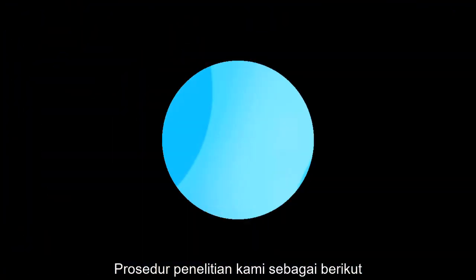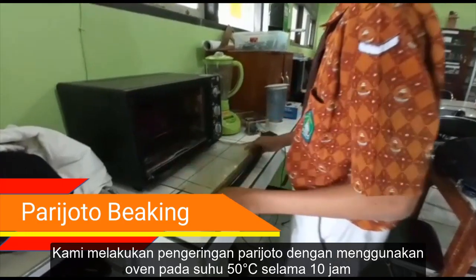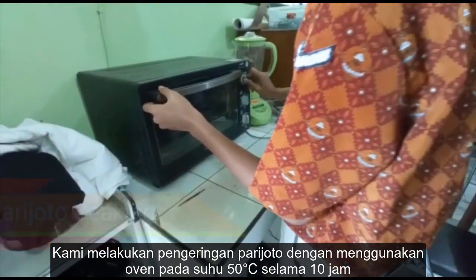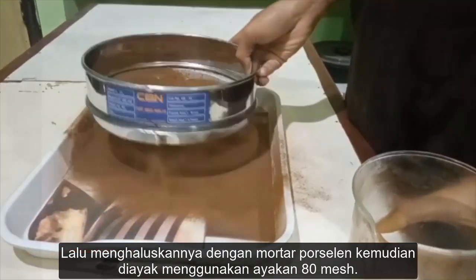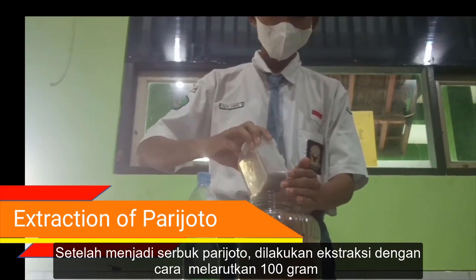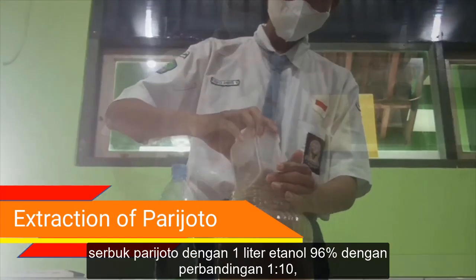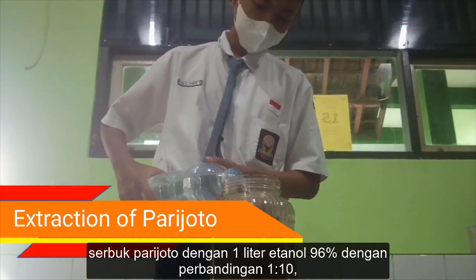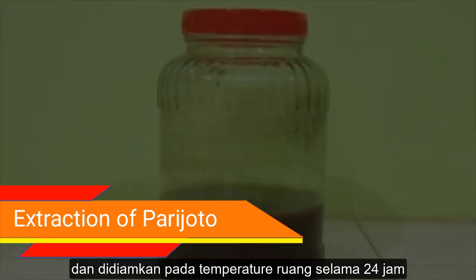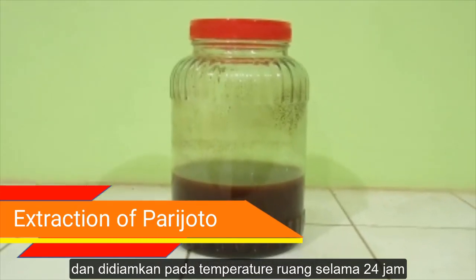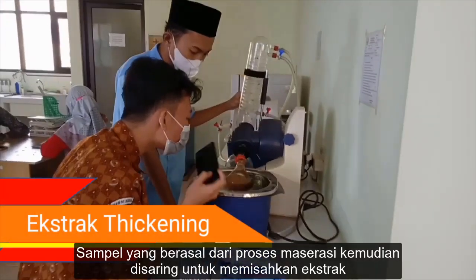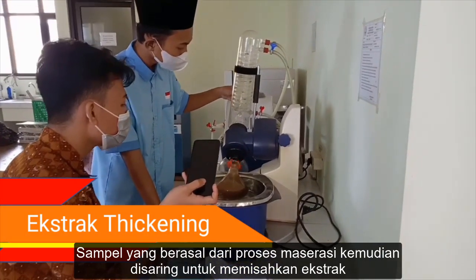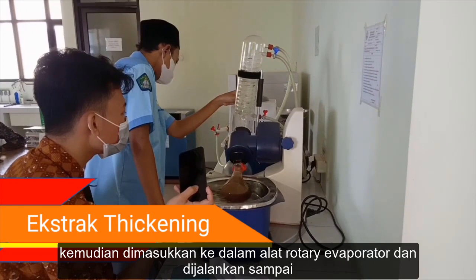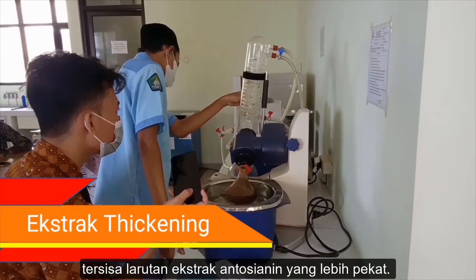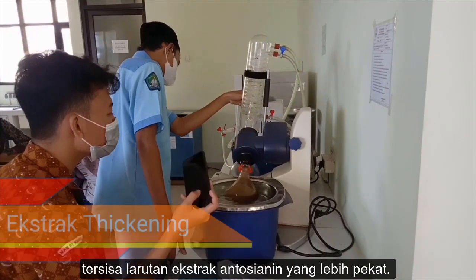Our research procedures are as follows. We dried the parijoto using an oven at 50 degrees Celsius for 10 hours, then ground them in a porcelain mortar and sieved them using an 80 mesh sieve. After becoming parijoto powder, we did the extraction by dissolving 100 grams of parijoto powder with 1 liter of 96% ethanol in a ratio of 1 to 10 and allowed it to stand at room temperature for 24 hours. The sample from the maceration process was then filtered to separate the extract from the filtrate, then put into a rotary evaporator and run until a more concentrated anthocyanin extract solution remains.